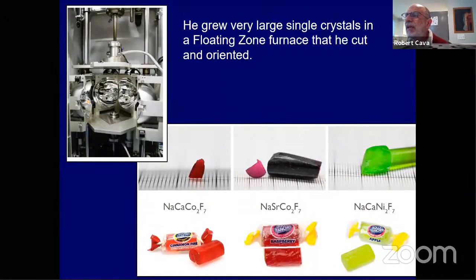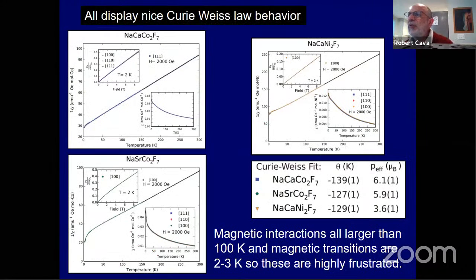And he made crystals. And here are Jason's fluoride pyrochlores based on cobalt 2+, and nickel 2+ here. And they grow nice big crystals in the floating zone furnace. Here's a picture of the floating zone furnace. So after you figure out how to get the fluorides clean, then you have to do a mixture with other fluorides to make it work, make the charge balance work. And these things are spectacularly frustrated magnets.